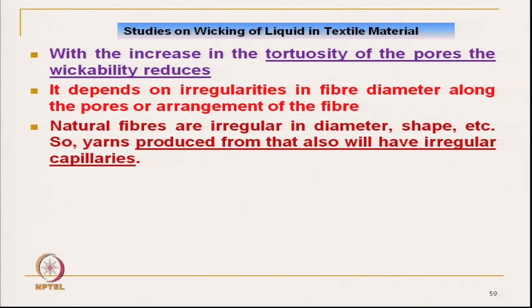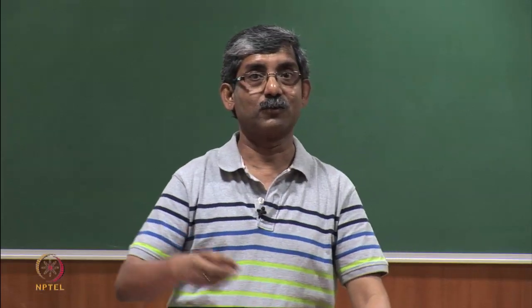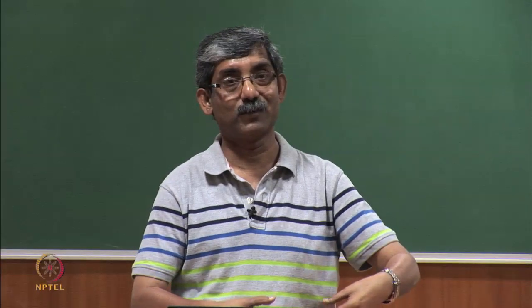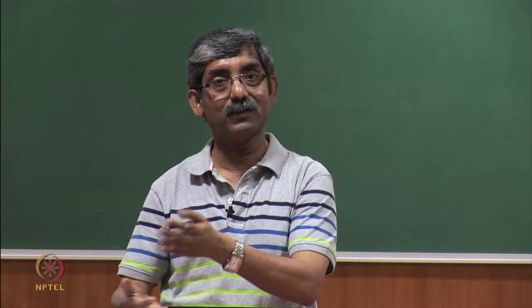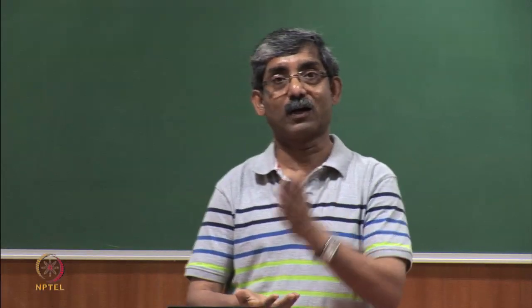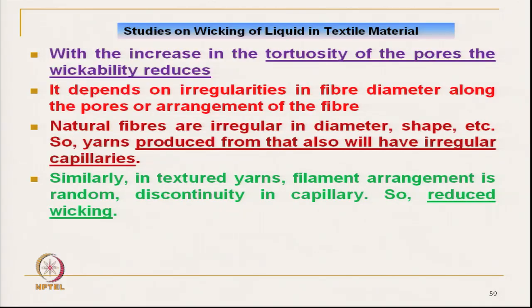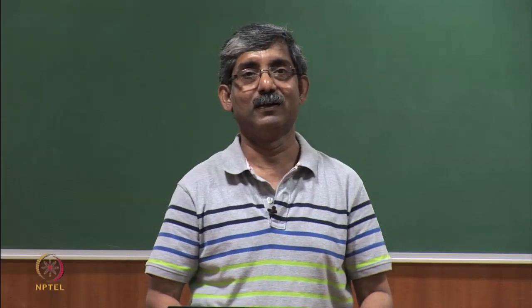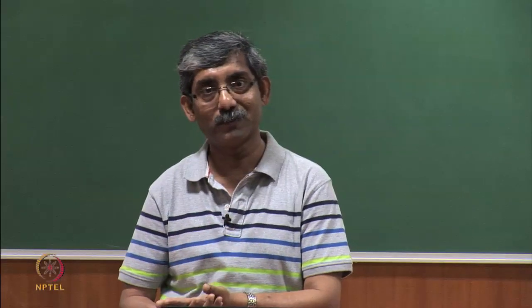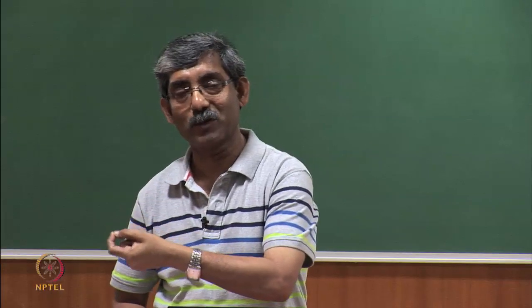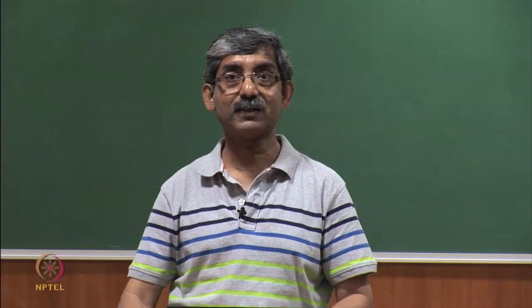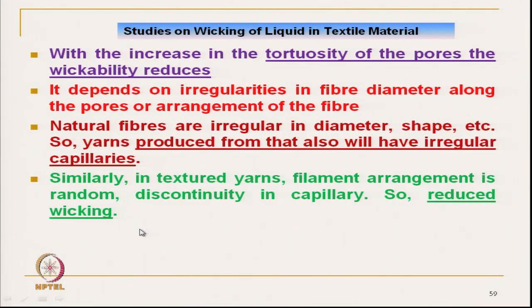So, if we talk about natural fiber or multifilament fiber, the pore geometry, that is the capillaries, are totally irregular in natural staple fiber yarn, and these are not continuous. This actually affects the wicking characteristics. Also for polyester filament, if we make the textured filament, its tactile characteristics improve, its softness improves, but liquid moisture transmission is reduced. It reduces wicking because of the discontinuity and non-uniformity in the capillary channel. So, the total capillary pressure generated will be reduced and capillary flow will be reduced. So, wicking characteristics will be reduced.